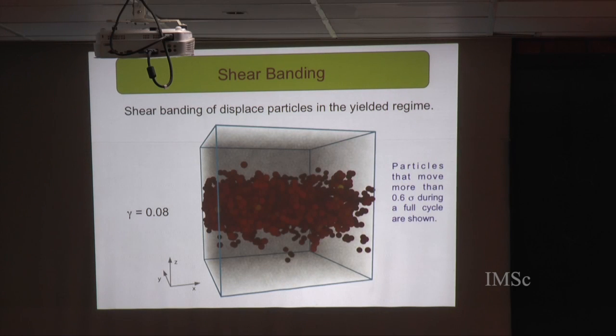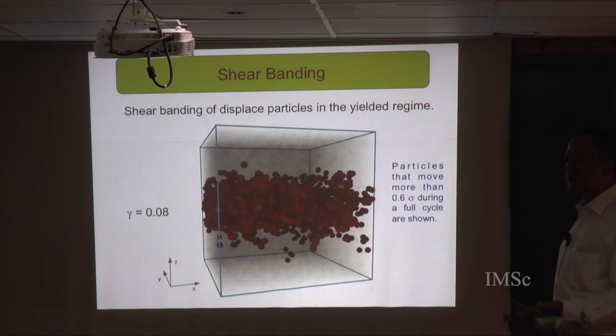But let me end by talking about shear banding. If you look at the set of particles which participate in plastic events, now focusing on amplitudes above the yielding amplitude, what you see is that they do form shear bands. These shear bands are not present below the yielding transition.